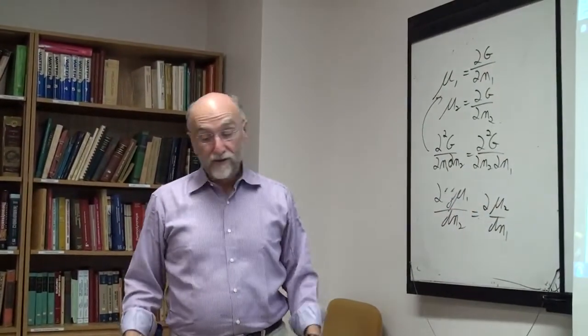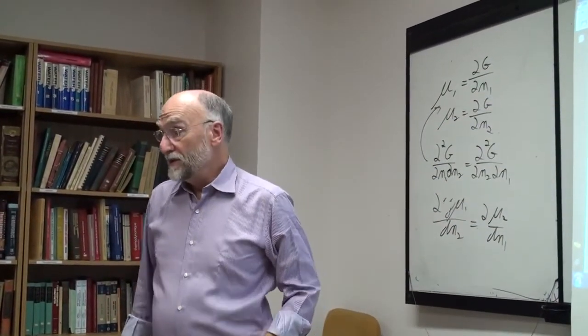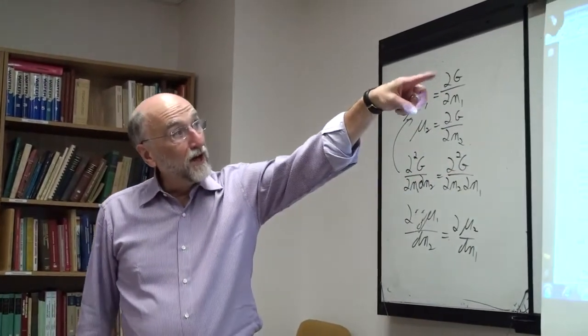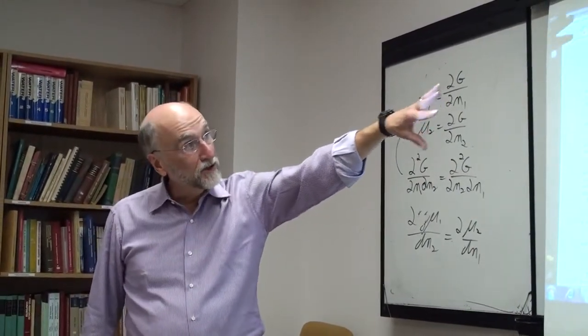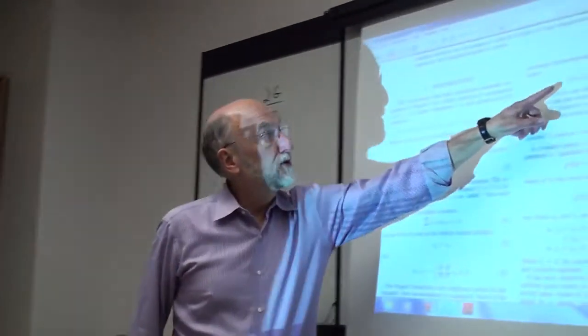So Wagner's formalism is used with the recognition of this problem, meaning the further away you get from infinite dilution, the worse the formalism is. It's not just that the log gamma of the solvent doesn't work. Independently of what you write for log gamma solvent, those two expressions for log gamma 2 and log gamma 3 are not consistent with this relationship number 7. So even for log gamma 2 and log gamma 3, except at infinite dilution, they are not consistent with a necessary thermodynamic relationship.